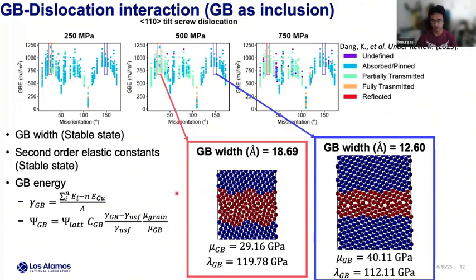This is just the case for the isotropic cases. And these are the elastic constants of my grains. So you can see, for instance, for these cases that you have a softer grain boundary, but also a harder grain boundary.